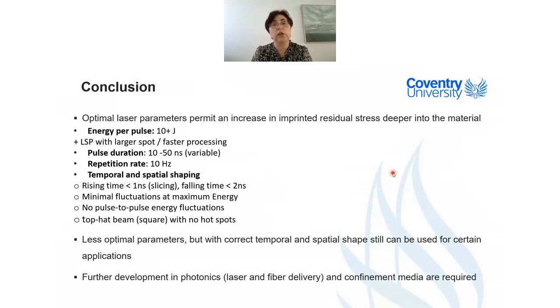As I said, we were also working on the possibility to minimize the printing time. So we increased the printing layer. All of these ones are without laser shock peening, while this one with full symbols is peened. And obviously the best performance we had was for the most optimized EOS process on which we added laser shock peening. But you can see that, for example, for this 60 microns printed, if we do laser shock peening, we were able to get very similar results to the other MEM or EOS optimized processes.